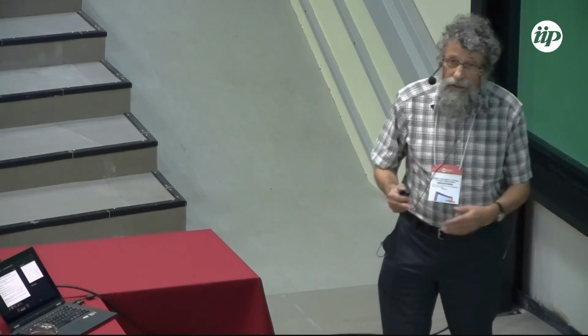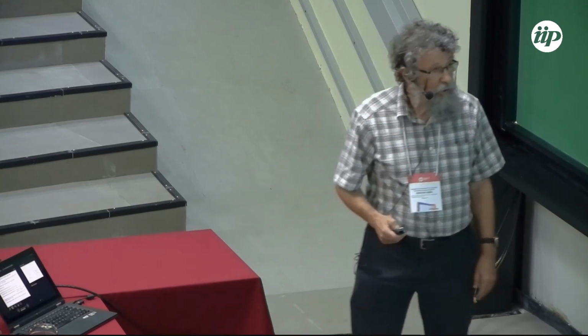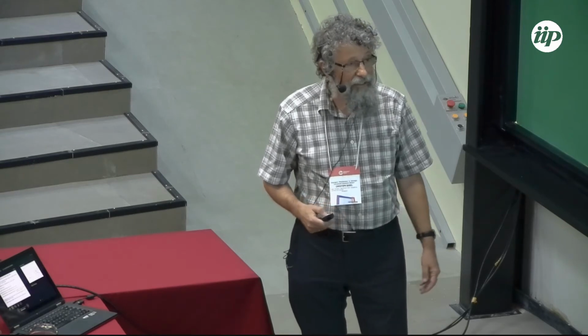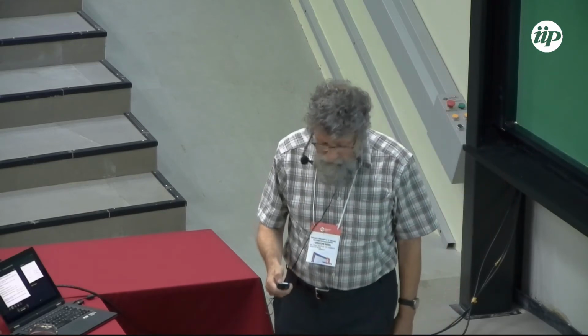But we know that if you have, for example, 1% exchange, you will not see it with this technique. And we know from CeCu2Si2 that this can completely change the story. Therefore, unfortunately in some sense, it is clear that we need an extended long-term research to clarify the composition dependence, to look at the intrinsic properties and the nature of the transition. There is already an accepted proposal for looking with μSR to see where we have a magnetic transition and where we do not. So we certainly need further measurements to confirm whether the superconductivity is intrinsic or not.